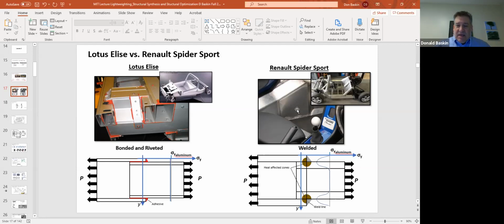So the difference is that because Lotus used an adhesive to bond together the extrusions, there was no heat affected zone. Whenever you weld something, you damage the material by heat. You change the intended microstructure to another microstructure, which may or may not be strong. Usually it's not as strong as the base material, and you end up with a weaker material. So Renault, in order to compensate for this reduction in strength, had to use a much thicker wall extrusion.